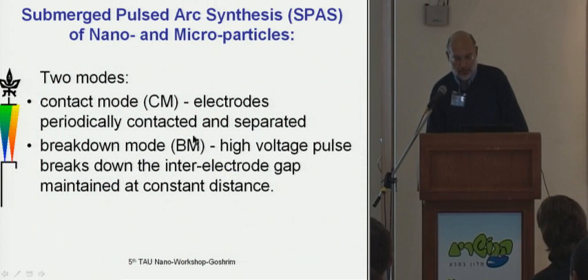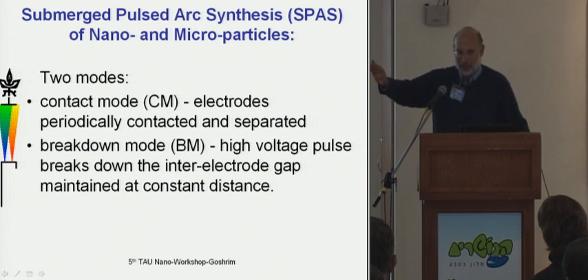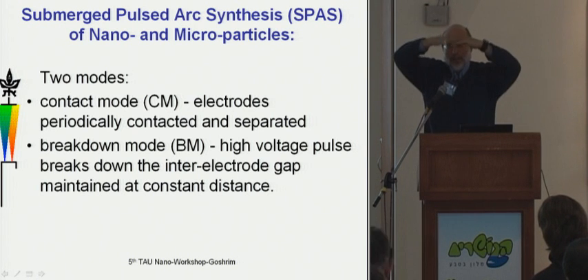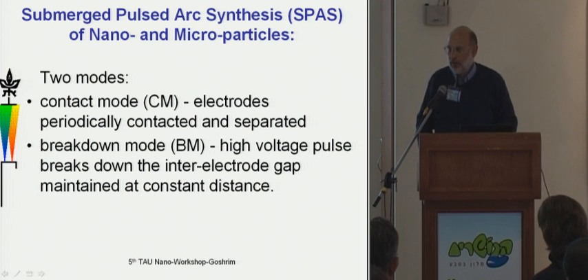Now, we actually do this in two modes. What I showed in the little movie was a breakdown mode, in which we applied high voltage between fixed electrodes. It's actually more convenient to work in what we call the contact mode. Basically, we have a vibrator, and don't get your ideas up here. One electrode is connected to a vibrator, and it's contacting the other electrode at a frequency of about 100 hertz.